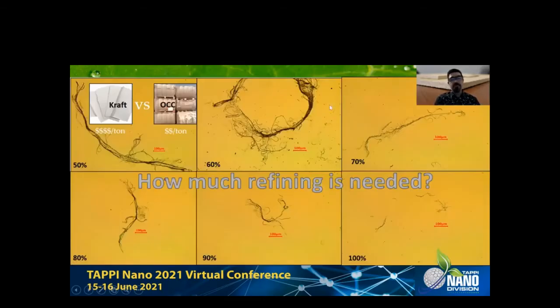So one big question here is how fine your nanocellulose should be so that it can do the bonding for you. We know that nanocellulose, as it is produced at the PDC at the University of Maine, is basically a mechanical process where you put cellulose and water in, and you apply energy, and you get your nanocellulose. The regular nanocellulose is produced at 90% fines, but you can produce it at any fines content that you want, and you know that if you go further, you need more energy.